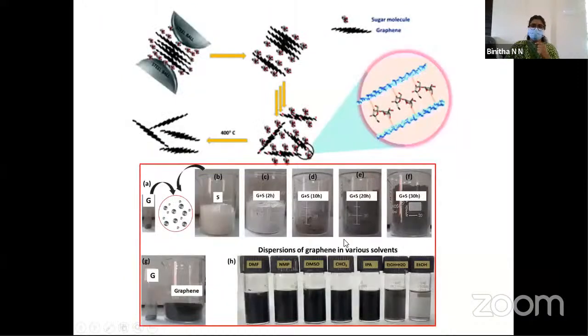These are photographs of different stages of ball mill exfoliation of graphite with the sucrose. The carbohydrate moieties can additionally stabilize the graphene sheets, and it will lead to exfoliation. And this graphene is dispersible in various organic solvents. It can also be mixed with water before calcination for producing aqueous processable graphene.